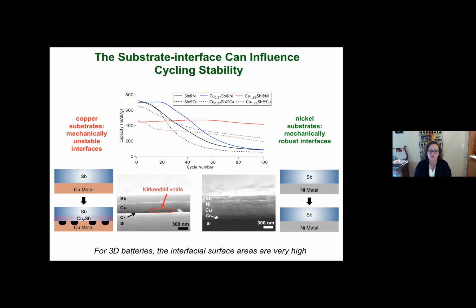But if you do that, the copper diffuses from the current collector so quickly, you form Kirkendall voids, which is what I'm showing you in the cross-sectional SEM at the bottom of the slide. And those voids weaken the contact between the active material and the current collector. If you deposit, say, a very thin layer of nickel metal, the nickel doesn't diffuse. You can cycle that battery for a very long time and you don't get this mechanical weakness.